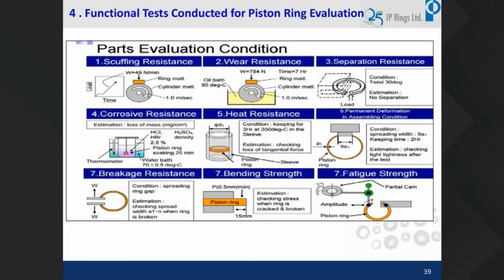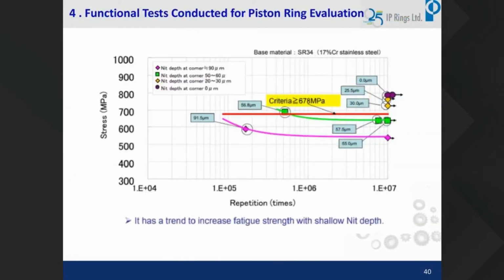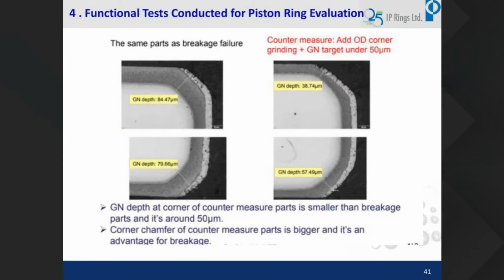Other tests mostly will not be covered in mechanical testing, but the fatigue test will be covered under mechanical testing, which I show next. I have a case study which I'll show. When there was a phase change from BS4 to BS6, we had to supply to Tata Motors for an engine application. At the BS4 stage, the ring thickness was around 2 mm, and when it changed over to the BS6 phase, the designer suggested 1 mm. That is the customer's design, and it was reduced to 1 mm.